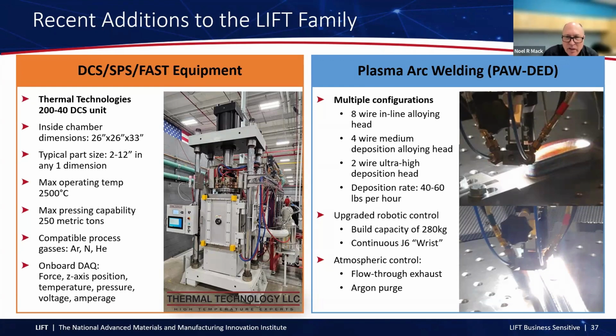On the right is a more recent add, which is our plasma arc weld DED cell that we've stood up. This can run up to 8 wires simultaneously to either alloy on the fly or produce functionally graded structures. We can run this in an 8-wire, 4 or 2-wire mode and put down materials at up to almost 60 pounds per hour with a hot wire insert on the 2-wire feed. We can also run this with shielded gas or with a fully inert environment. So we literally flood the entire cell, purge it from the bottom up with argon, so we can run in a full inert environment if we need to.